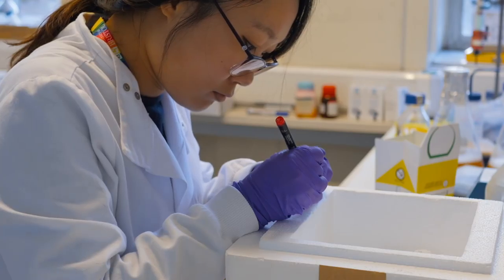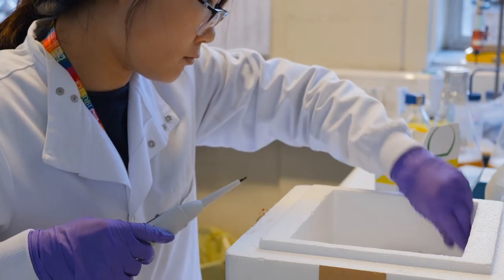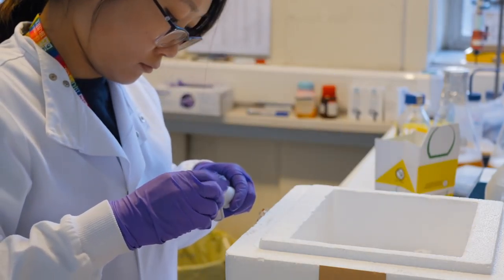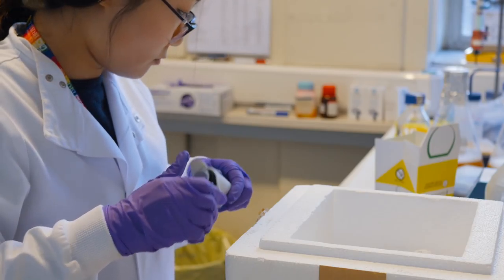The cell types we use are adult stem cells, taken from donors from the Bristol Royal Infirmary. We print the cells while they're still in a stem cell state, then introduce growth factors to convert them into cells that produce cartilage, called chondrocytes. We're able to carry out this entire process - which takes about five weeks - and grow the structures into human cartilage, which we then analyze to see how it compares with natural human cartilage.